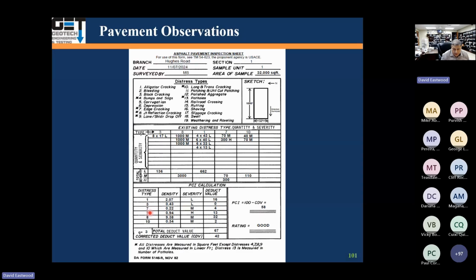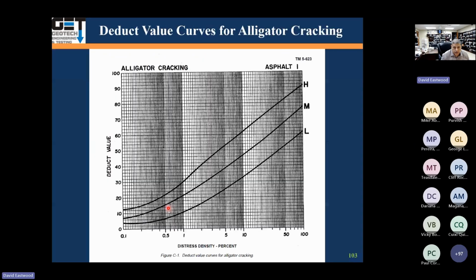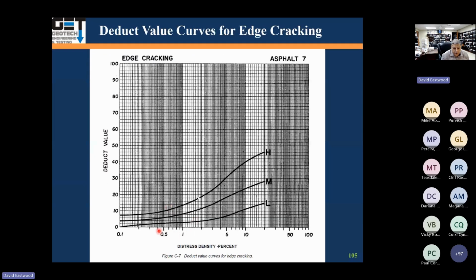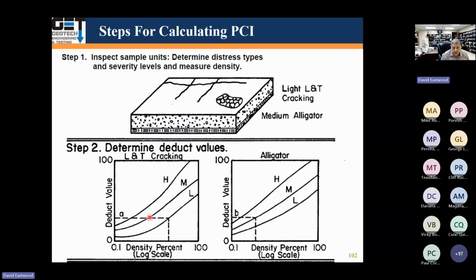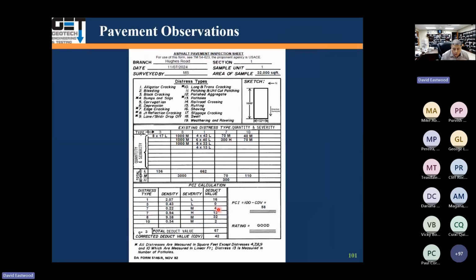You go to distress type number 7, edge cracking. Okay. One of them was medium 0.22. So you go to edge cracking 0.22, and that was medium. You should get somewhere about 5 or so for medium. So going back here for medium, you get 4. So anyway, you go through each one of these distress value areas, and you add them all up, and you get a total deduct value of 67.